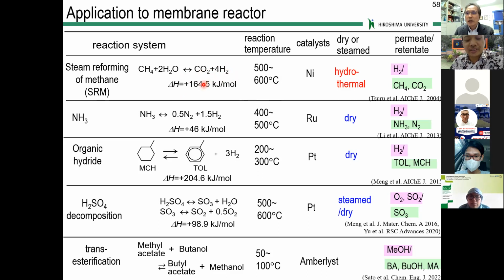What is the average pore size, Sensei, for the membrane for separation of hydrogen? Yeah, the size should be around 3 angstroms. The CO2 size is around 3.2 angstroms. The hydrogen is 2.89. So the pore should be between the two species.